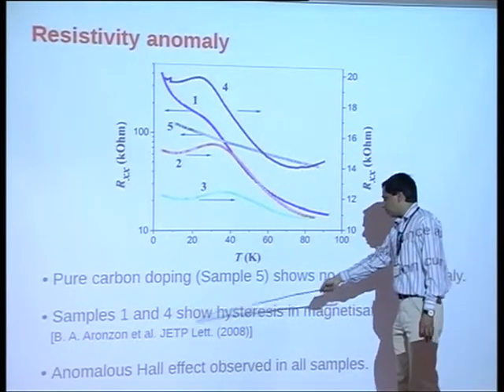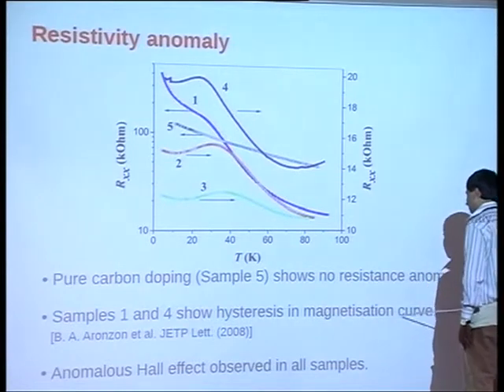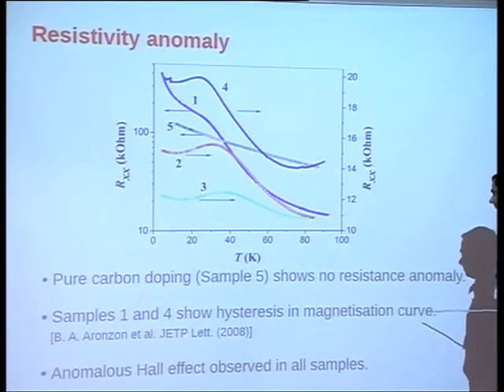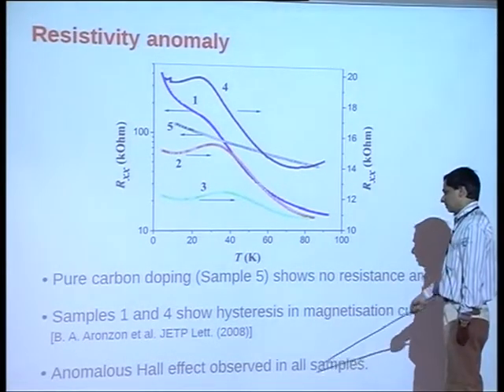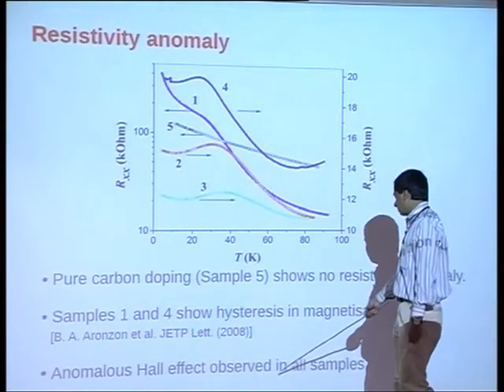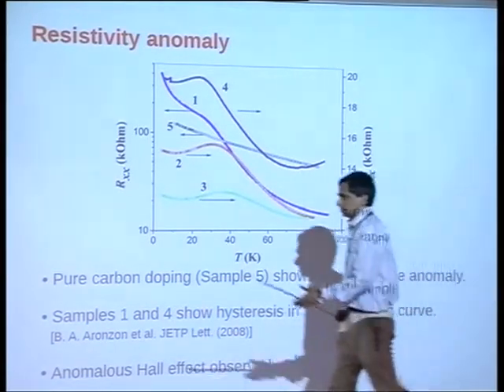Samples 1 and 4 also show hysteresis in magnetization at low temperatures. And now finally, anomalous Hall effect is observed in all the samples.